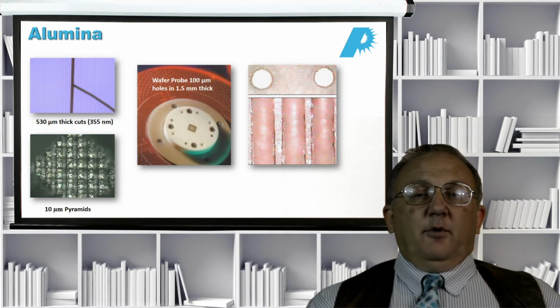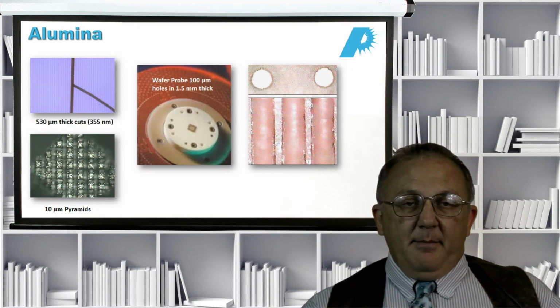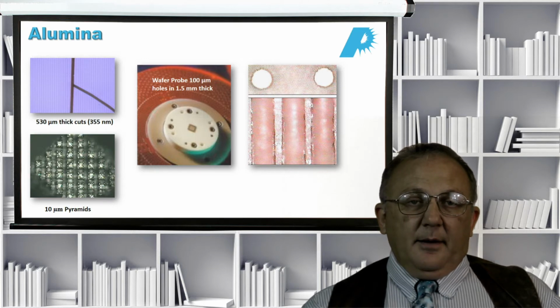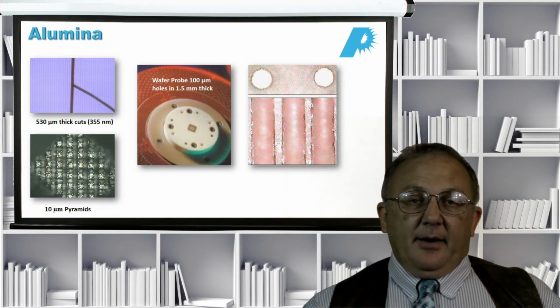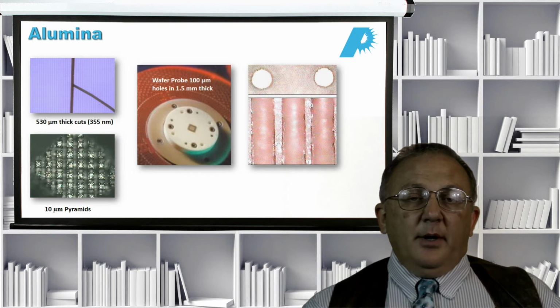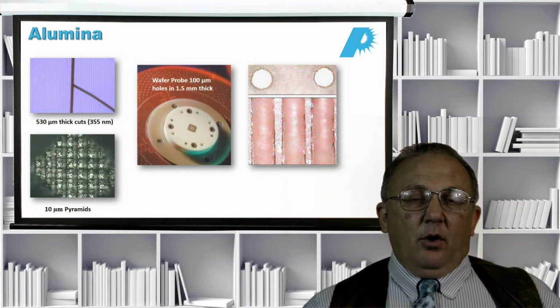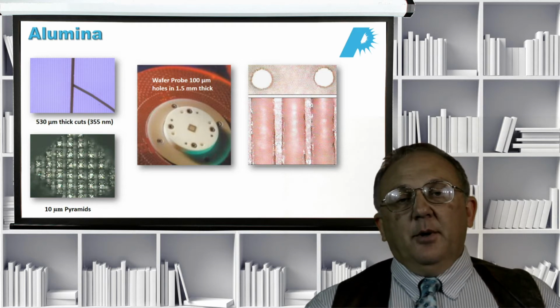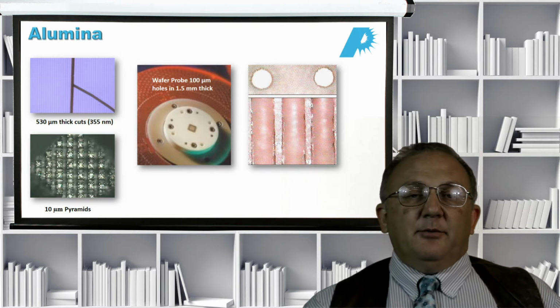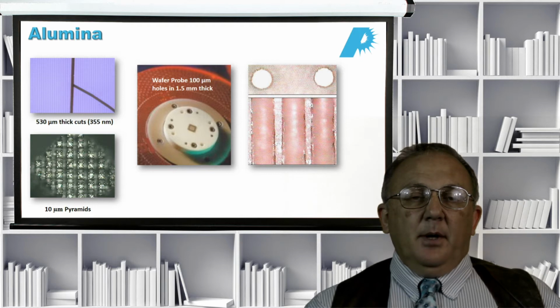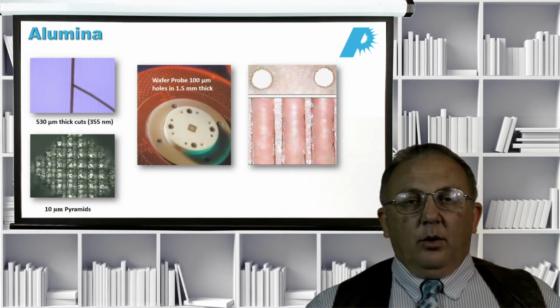Alumina is another very good material for working with. It's commonly used in many different applications, especially in the medical and also the electronics areas, sometimes in the semiconductor areas. In the middle you see a semiconductor probe, in the middle of which are drilled about 1,000 different holes. And those holes were drilled with a UV laser. On the right hand side of the screen you can see approximately a 4 mil diameter hole. It's about 4.2 mils at the top, 3.8 mils at the bottom. And by the way, 4 mils is about 100 microns if you like the metric system. And this was drilled through over 1 millimeter thick ceramic. So we kept a fairly high aspect ratio throughout that whole drilling process.